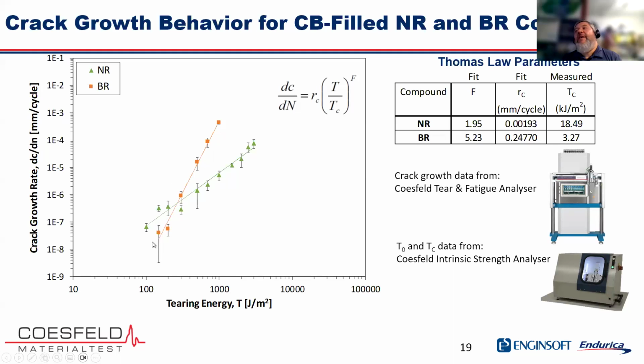And so, in fact, at very low loads, it's actually the case that the butadiene rubber has a higher fatigue threshold than the natural rubber. And so if you have an application that is operating at low load and never sees larger loads, you might actually choose the butadiene rubber because it's going to give you a bigger fatigue limit. So like I say, you need to be a little bit careful to evaluate when you're choosing materials. You need to take into account how much load you're putting on the material.